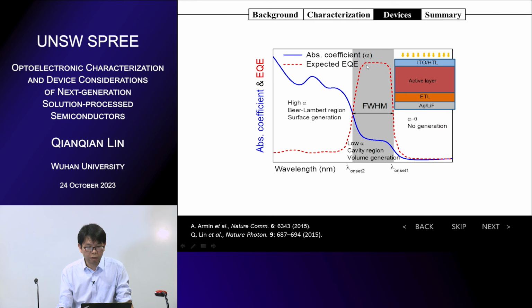If you have low alpha, then the light can penetrate much deeper. It generates carriers in the bulk. So the surface generated carriers take a longer distance to be collected, and the bulk generated carriers need a shorter drift distance. So if you can tune the charge transport processes, you can selectively collect the bulk generated carriers, but not collect any surface generated carriers. Then you will get a photo response like this, the red dashed line.